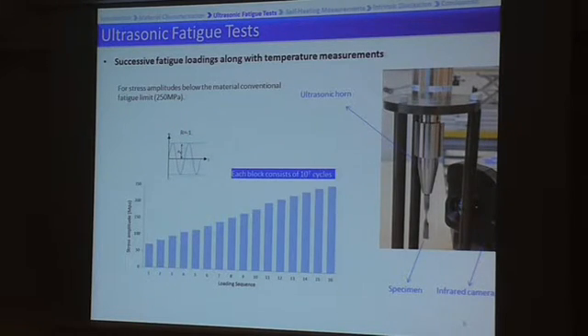And there was a gap of around 10 minutes between two successive steps in order to assure that we start in the equilibrium state. Moreover, as I mentioned before, the maximum stress amplitude in our case is around 247 megapascal, which is under the fatigue limit of the specimen, which equals 250 megapascal. And each block of loading consists of 10^7 cycles. So we did the fatigue test at each step, and we captured the temperature on the surface of the specimen, and also after stopping the load, we continued the measurements of temperature to capture the cooling part of the specimen also.